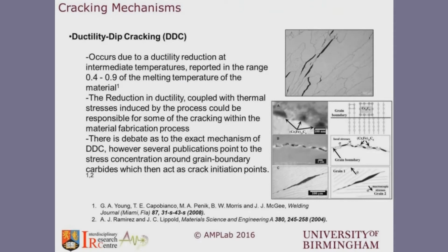The third mechanism, which is reported a lot in nickel superalloys literature, is the mechanism known as ductility dip cracking, which is believed to occur as a ductility reduction for the material in intermediate temperatures. This reduction in ductility seemed to exist in the grains that show, as you can see on the top right-hand side micrograph, fairly straight boundaries.